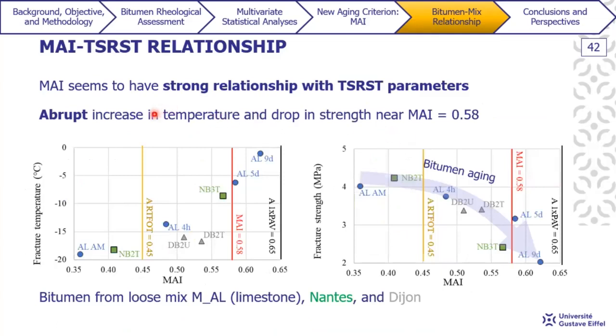And MAI also seems to have a strong relationship with the TSRST parameters. Here we have fracture temperature versus MAI, as well as fracture strength versus MAI. And you can see an abrupt increase here of this trend of the fracture temperature and an abrupt drop when these values get closer to the 0.58 value that was the tentative failure criteria that was proposed for the MAI. And just to inform that the black markers represent the loose mix that was aged in the laboratory. The green one was from Nantes section and the gray one was from Dijon.